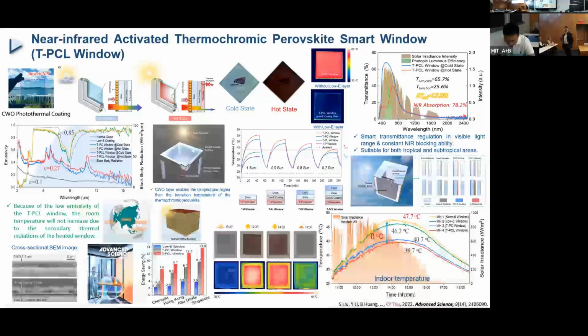This solves the humidity problem of the perovskite material. You can see that even under 0.7 sun, the window temperature can reach about 40 degrees Celsius and trigger the transition temperature. Then you may argue that the window itself may become very hot after absorbing the near infrared. That is why we also add a low-E coating, so that the window itself will not emit radiation to the indoor environment. You can see the emissivity in the mid infrared region of this TPCL window is about 27%, which is very low and close to low-E windows.